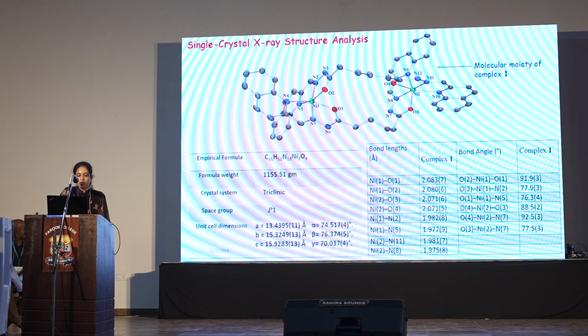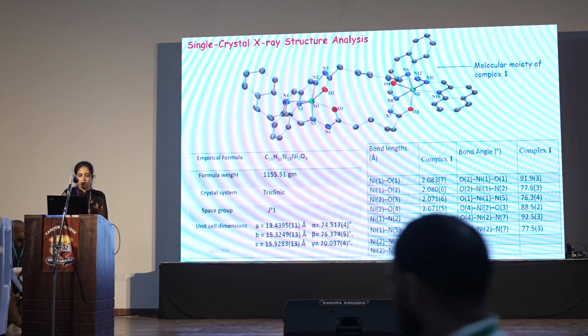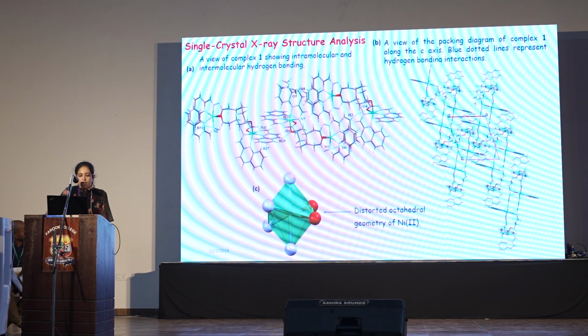Further, we have established the structure of the complex using single crystal X-ray analysis. Here also the complex crystallizes in triclinic crystal system with P-1 space group. Here, figure A shows different intermolecular and intramolecular hydrogen bonding interactions with the packing diagram of complex 1 along the c-axis, and figure C shows the coordinating atoms of the nickel atom.